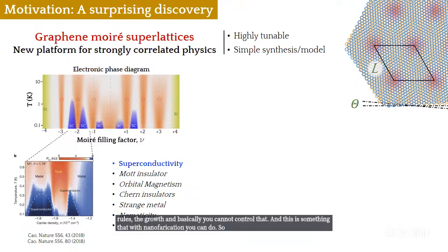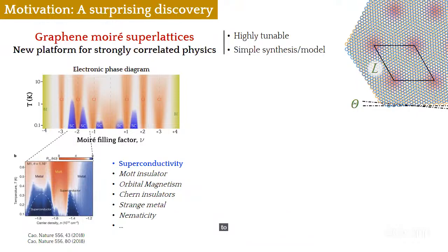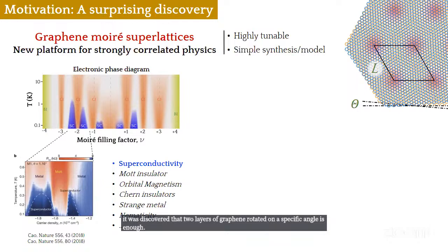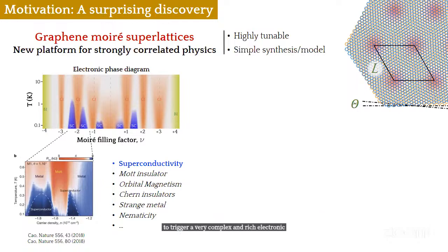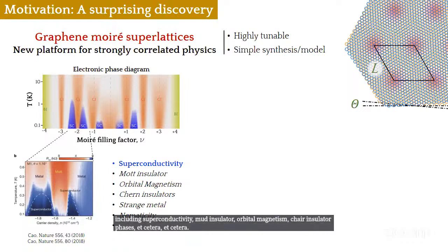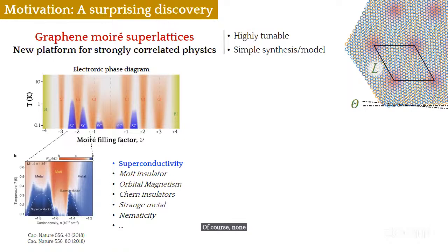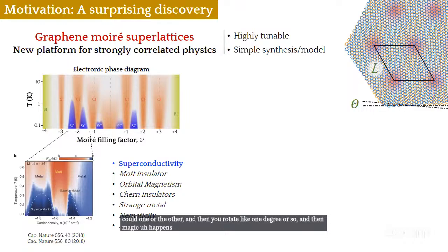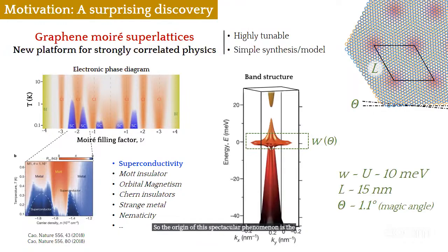So the origin of the motivation for us to do these kinds of samples is the following. Five years ago, more or less, it was discovered that two layers of graphene rotated at a specific angle is enough to trigger a very complex and rich electronic phase diagram, including superconductivity, Mott insulators, orbital magnetism, Chern insulator phases, etc. Of course, none of these new phases take place in bare graphene. So you basically simply put one on the other, and then you rotate one degree or so, and then magic happens. The origin of this spectacular phenomenon is the flattening of the bands as you rotate in between.